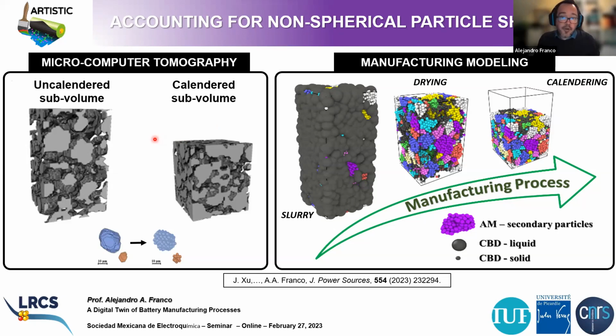So we have characterized electrode microstructures before calendaring and after calendaring, using micro-CT, microcomputer tomography. And in such a way, we can extract families of particle morphologies. And then in each of these particle morphologies, we embed a collection of spherical primary particles, reproducing the overall morphology of a secondary particle. And then we apply the same MD-like framework I described before. That means we account for interaction forces between primary particles with different magnitudes for the primary particles belonging to the same secondary particle versus the case where these primary particles belong to different secondary particles. In such a way, we can simulate the entire manufacturing process, therefore the slurry, the drying, the calendaring, by using non-spherical particles.